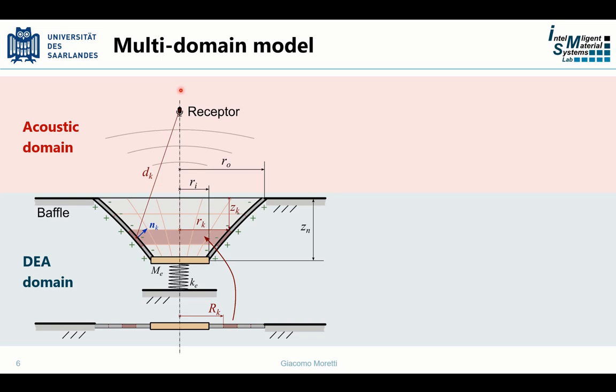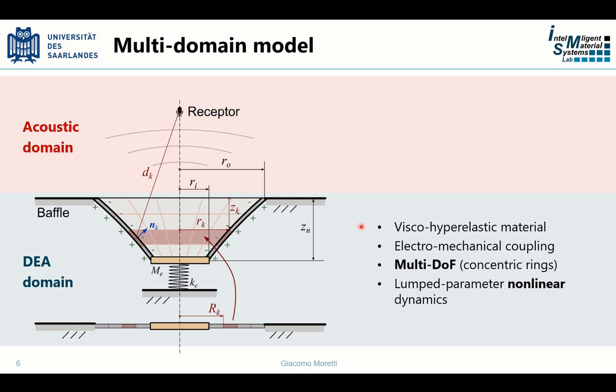For the DE we used nonlinear visco-hyper-elastic dynamic models, and in particular, to describe the structural dynamics, we used a multiple degrees of freedom approach. We ideally break the membrane into a set of rings and we study the dynamics of each ring.